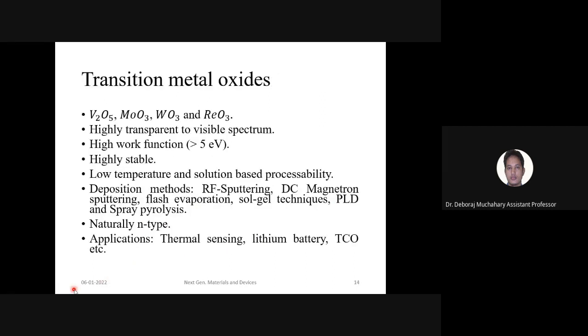Next we'll see transition metal oxides and the current scenario: what people have done up to now. V2O5, MoO3, and WO3 are highly transparent to the visible spectrum, as I have already mentioned. They also have a high work function of around 5 electron volt. Work function is also a very important parameter, because it helps in the flow of charge carriers. If the work function is matching, then the flow of charge carriers is good. Otherwise, if there is a barrier, it is not good for transmission. So these transition metal oxides have a high work function, which is good for transmission of the charge carriers.